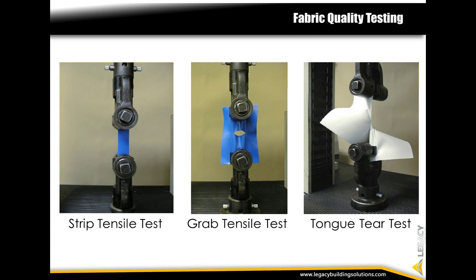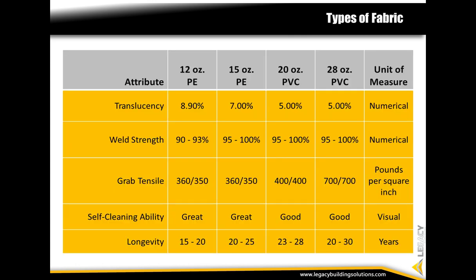Architectural fabrics are subject to several quality tests. These tests measure the strength of the fabric by determining the force or load which causes the fabric to break and how long it stretches or elongates before breaking. In addition to strength, fabric is measured for flame and UV resistance, uniaxial and biaxial elongation, coating adhesion, and weldability and seam strength.